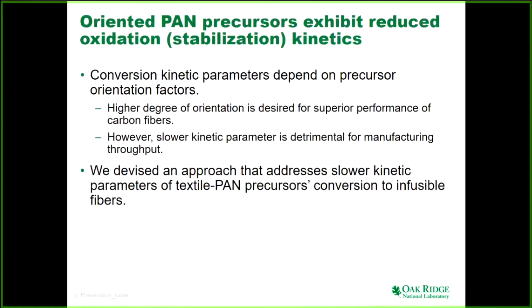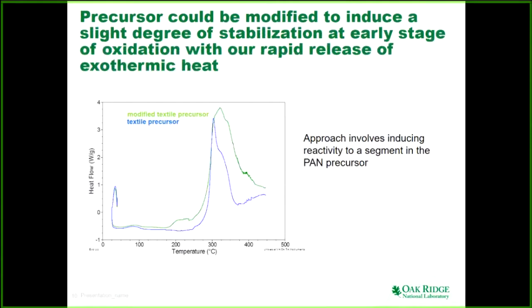So we devised an approach that addresses slower kinetic parameters for textile or any other precursor in converting it to infusible material. This is differential scanning calorimetry data. Basically, when you are heating this fiber in air, some heat is evolved because of the exothermic reaction. We monitor at what temperature the heat evolution starts. Now look at this textile precursor, the blue curve, whose onset is somewhere around 250 degrees Celsius, then a sharp rise in exotherm. That's why textile-based conversion is tricky. At what temperature would you oxidize and carbonize? Because when a lot of heat evolves, it may melt the fiber or break the fiber tow.